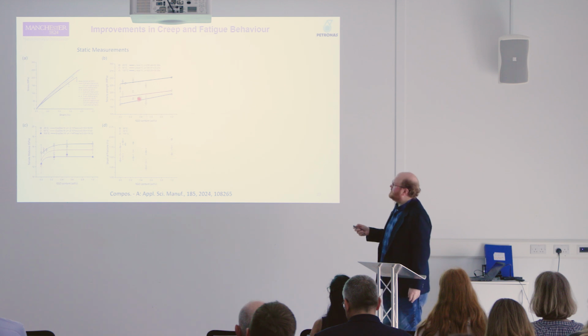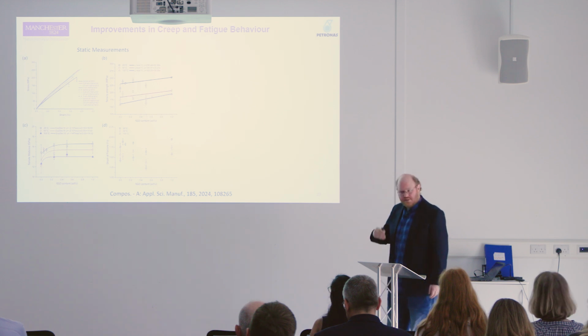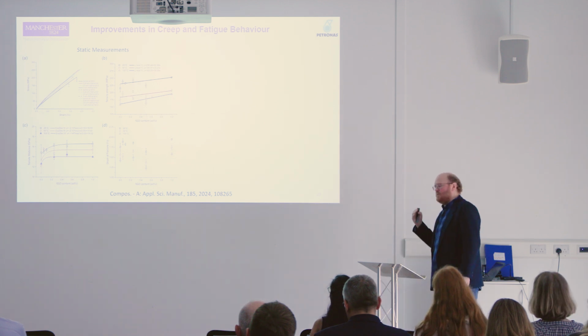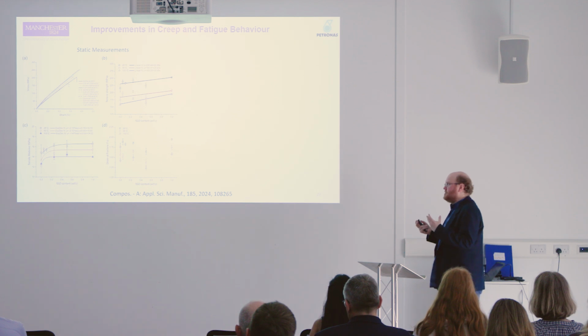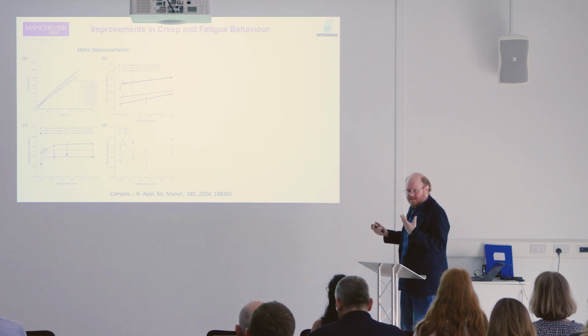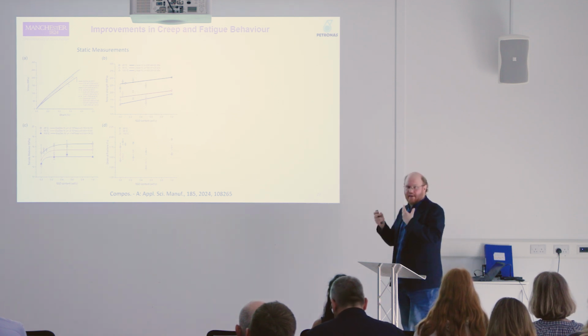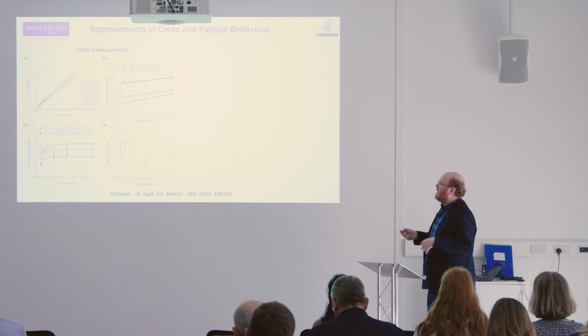These are at different temperatures. This is at room temperature and then at higher temperatures. And of course, as the higher temperatures get closer to the glass transition temperature of your matrix, in this case an epoxy, it can soften and then actually reduces its mechanical properties. So what we actually found was that graphene was more beneficial at those higher temperatures instead of just at room temperature. That the slope of this line basically is steeper at higher temperatures. So we would see more benefit when your matrix was starting to soften.